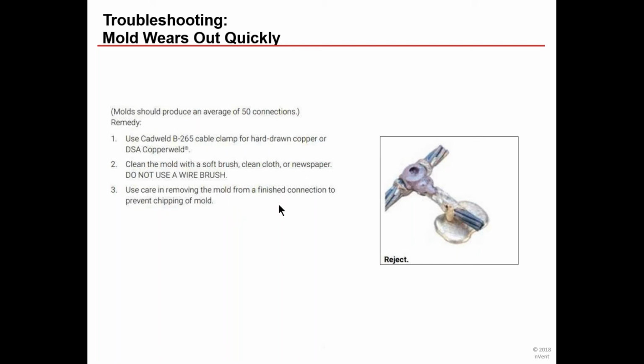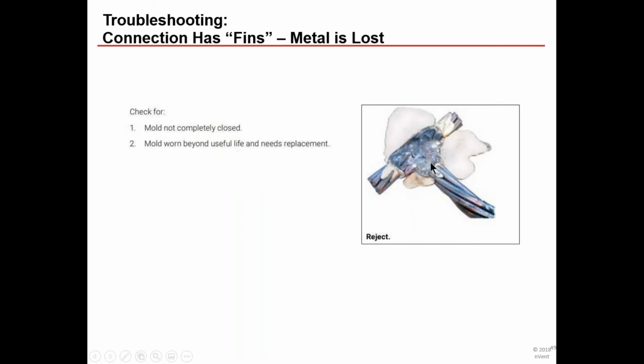And you have to be careful when removing the conductor as not to chip your mold. So here's where the mold may have been chipped, the wrong conductor was used, a lot of leakage came out, and your weld almost became half slag here, and it even fell in the middle. Here's one where you might have a weld, but you have fins. That's an indication that it's leaking out in between the two halves, or the separation of the mold, the opening of the mold. So again, check for the mold not completely closed, or it could be worn beyond its life and needs to be replaced. If it's definitely closed and you're getting something like this, it might be time to replace the mold.